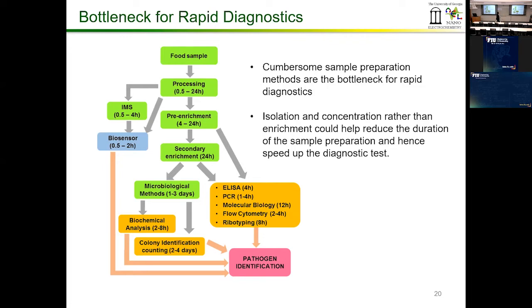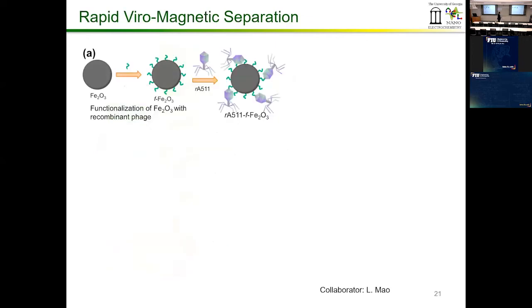So that's the challenge. These methods use enrichment of the bacteria, which means they're growing bacteria to increase their colonies. What we are interested in is to take the given amount of cells and try to isolate and concentrate them instead of enriching them. Enriching is the step that takes a longer time. So let me show you the methods that we used. We used bacteriophages because we want to only collect the target bacterial cells from our sample. We took magnetic nanoparticles, which are not truly nano, they're microparticles, and we functionalized their surface with these viruses.